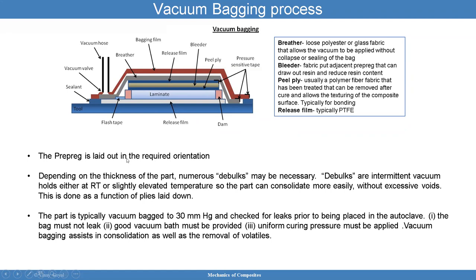The prepreg is laid out in the required orientation. And depending upon the thickness of the part, if you have a very thick part, you may require multiple debulks. And I talked about how debulks are basically trying to remove these voids through a vacuum process or some application of pressure. Debulks are really intermittent vacuum holds, either at room temperature or slightly elevated temperature, so the part can consolidate much easier. Of course, if you press two laminas together and there are any voids, if I press it hard, then the voids could come out. And then the cross-linking becomes more natural and more complete.